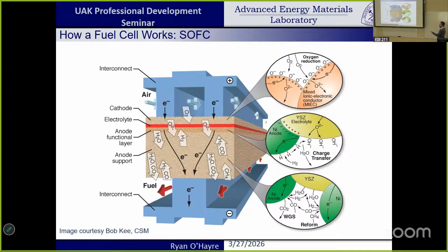So we basically make this thick anode, which is half a millimeter, 500 microns, maybe even a millimeter thick. And usually make them in square or disc, kind of button cell shapes. And then we deposit, various ways, the other 2 super thin layers on top. So the anode provides the mechanical support.